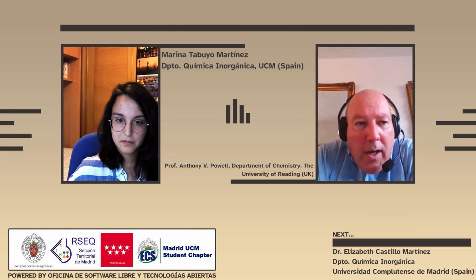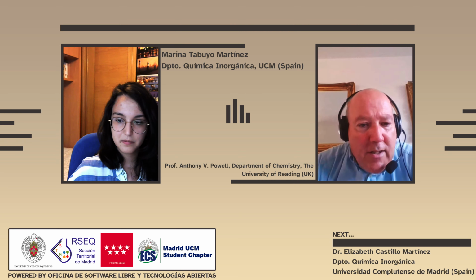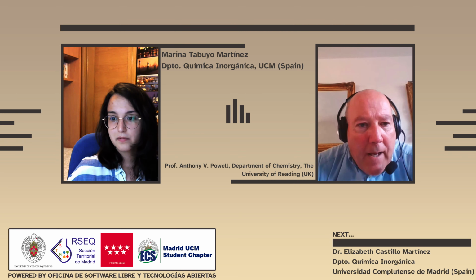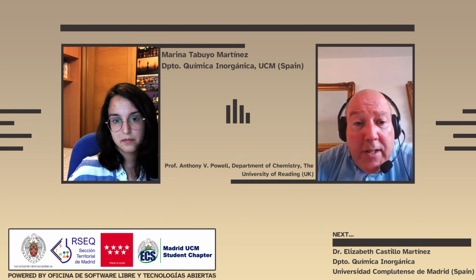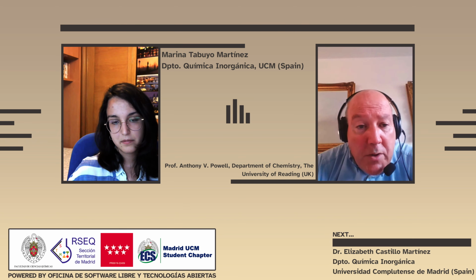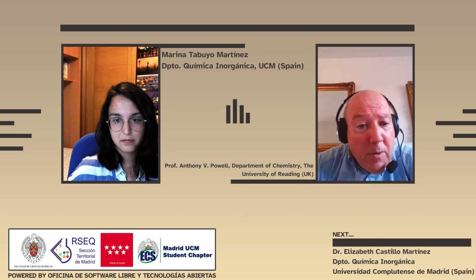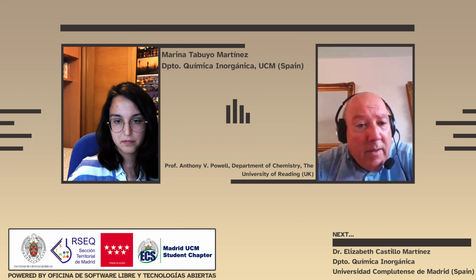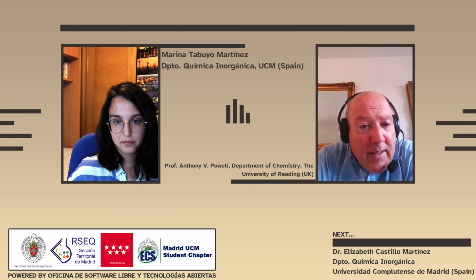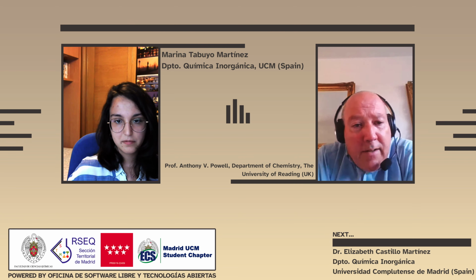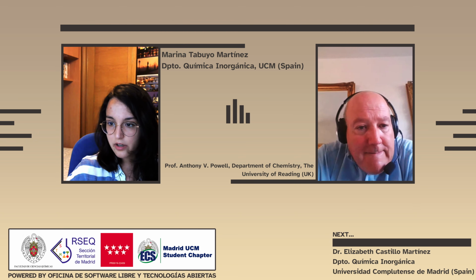And where we've struggled with the skutterudites is actually finding a solder that operates at the high temperatures where we'd want to use a module. So although we've got quite good performance, the performance, if we went up another 200 degrees, would probably be even better. But unfortunately, our solder melts by the time we get to that point. And it's a question of finding the right solder in order to get both good mechanical contact and good electrical contact.